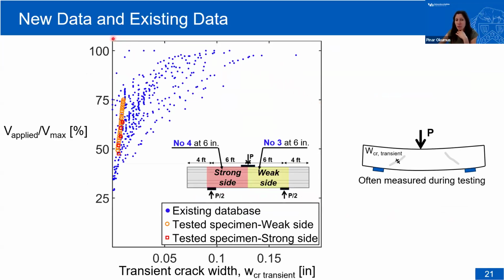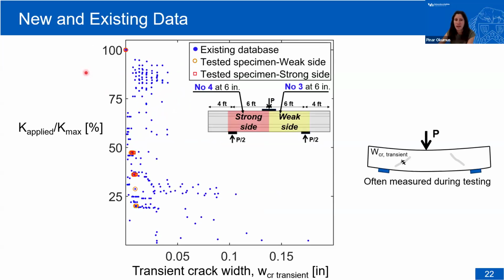This is the new data that we added to the database. So you're looking at the applied shear, again, normalized versus transient crack width. All the blue dots are what's available in the literature. What we've added is the colored points. So we added many data points to that plot. And then this is for the stiffness plot. So we added, again, many data points to that stiffness plot. You don't see as many here because a lot of the dots are on top of each other because they have the same stiffness for varying crack widths.